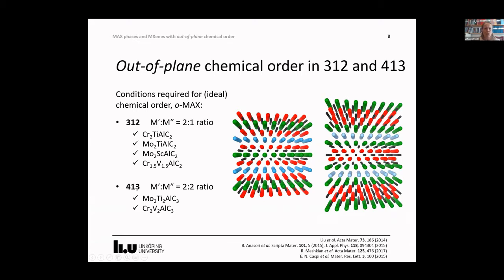Common for the 312 and 413 structures are the 2 crystallographically different M sites that we have. For 312, the first Wyckoff position is 4f. It is these red atoms here, also called M prime. And the second site is 2a. It is these green atoms here, called M double prime. Based on these two different sites, it is intuitively not surprising that we can get chemical ordering. And for an ideal o-MAX phase, we have a 2:1 and a 2:2 ratio for these MAX phases.